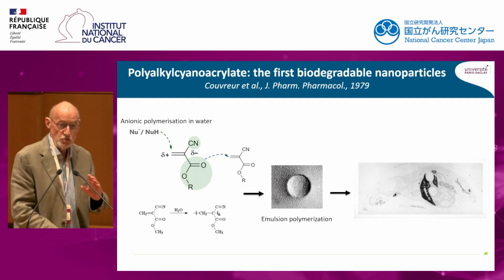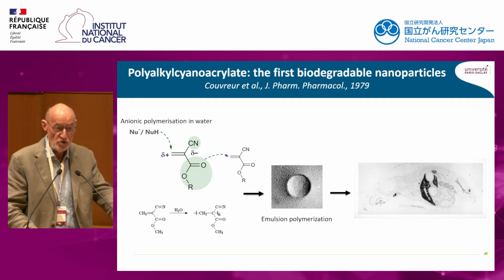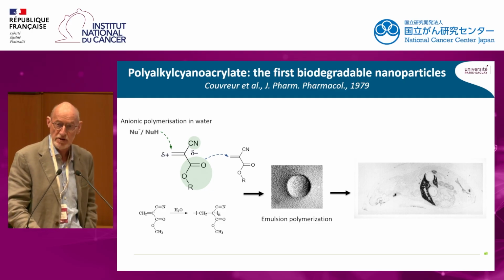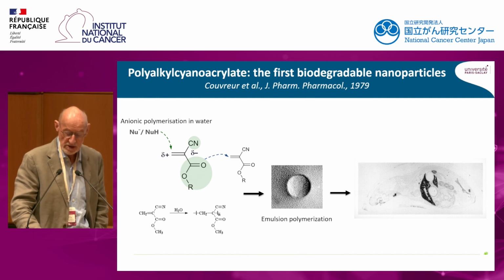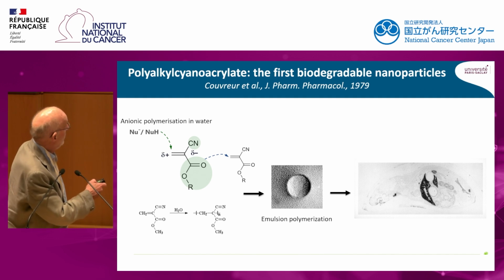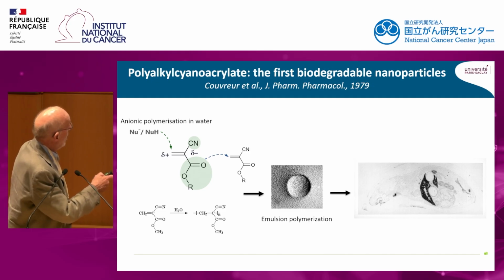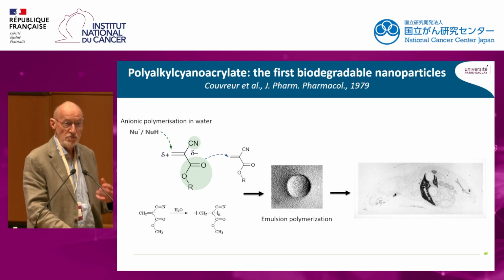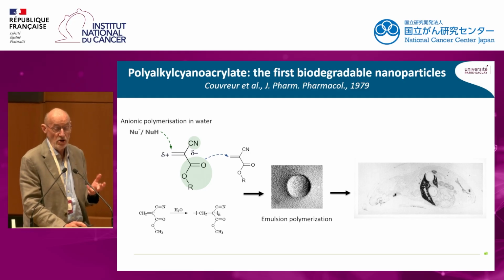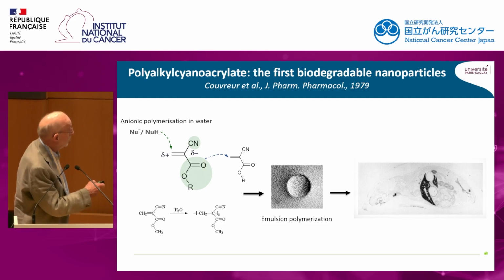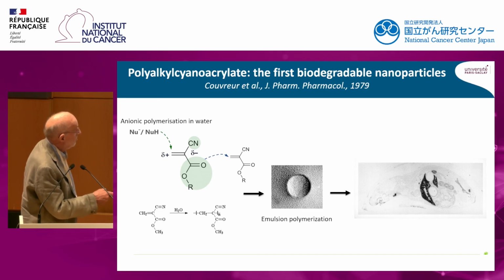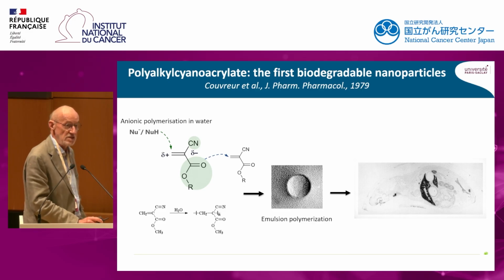So the first technology that we developed already a couple of years ago, as you can see, are the first biodegradable nanoparticles for human use based on polyalkyl cyanoacrylate. In fact, those nanoparticles are prepared by the anionic polymerization in a water medium of a cyanoacrylic monomer, which in fact is a biodegradable surgical glue. And so by emulsion polymerization process, this polymer is forming, as you can see here, nanoparticles with a size below or around 100 nanometers.